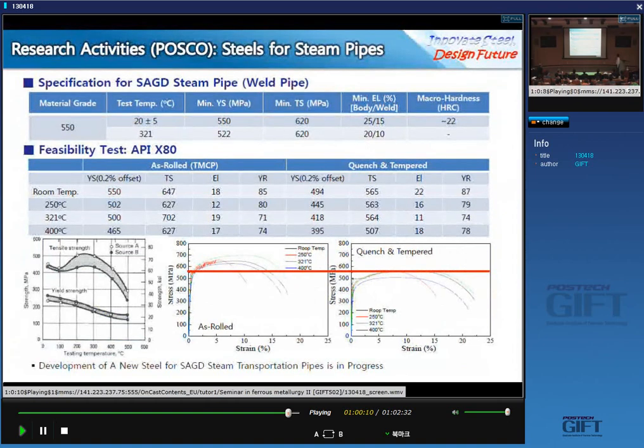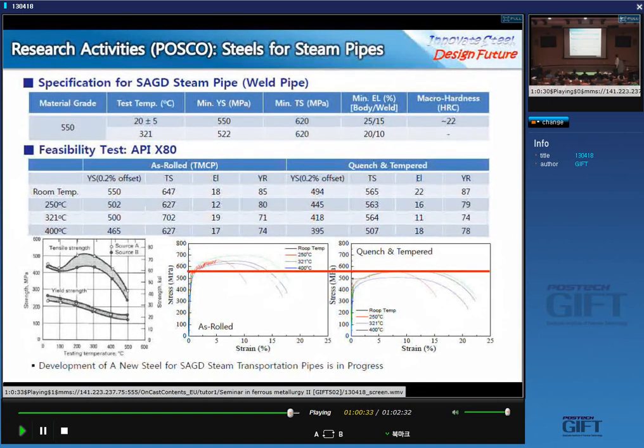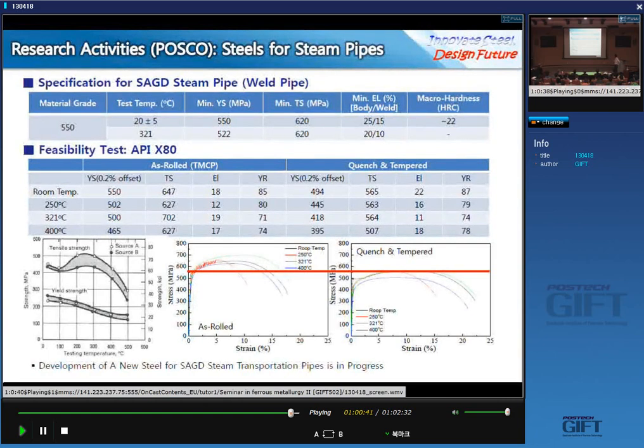Here is the requirement of the steam pipes. The material grade is 550 MPa, identical to API X80. We have to ensure high-temperature strength over 300 degrees Celsius. For a feasibility test, we started with our currently produced API X80, but as you can see the performance is not that good at high temperature — this is why we have to develop a new material, which we will work on in the near future.